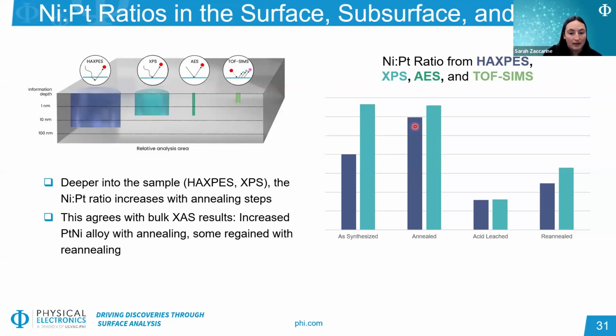And we had collected bulk X-ray absorption spectroscopy measurements to quantify that alloy. And we see a similar increase in the alloy when we have more nickel towards the surface. With acid leaching, our nickel to platinum ratio drops significantly, so we have a lot less nickel towards the surface, and then re-annealing brings some of that back. XPS in this lighter blue color has generally a similar trend, but the two first samples are slightly more similar, more towards the surface with XPS.